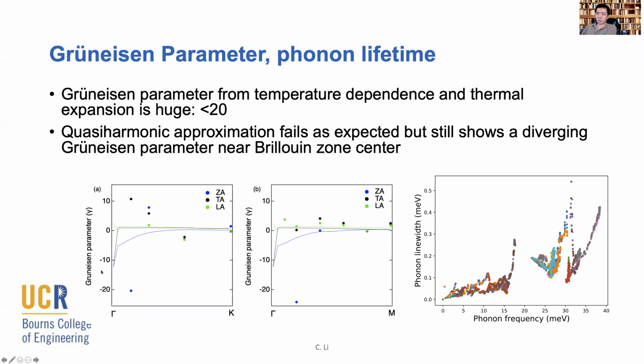And by the way, the Grüneisen parameter describes how the energy of the phonon will change in response to the volume change. And in this case, we are looking not at the traditional Grüneisen parameter. We're looking at its temperature equivalent. Basically, we are trying to evaluate how much the energy varies in response to the thermal expansion in the process. But you get a similar idea.